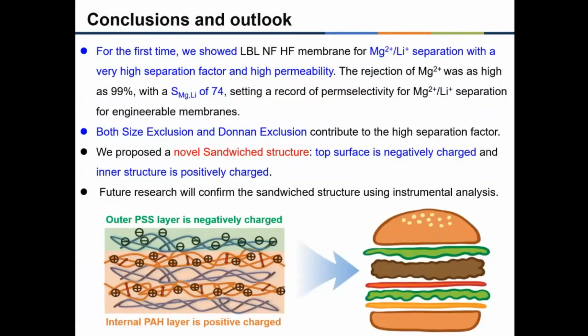To conclude, for the first time, we showed LBL nanofiltration hollow fiber membranes for magnesium-lithium separation with a very high separation factor and high permeability. The rejection of magnesium was as high as 99%, with a separation factor of 74, setting a record of permselectivity for magnesium-lithium separation for engineerable membranes. Both size exclusion and Donnan exclusion contribute to the high separation factor. We proposed a novel sandwich structure. The top surface is negatively charged, and the inner structure is positively charged. Future research will confirm the sandwiched structure using instrumental analysis.